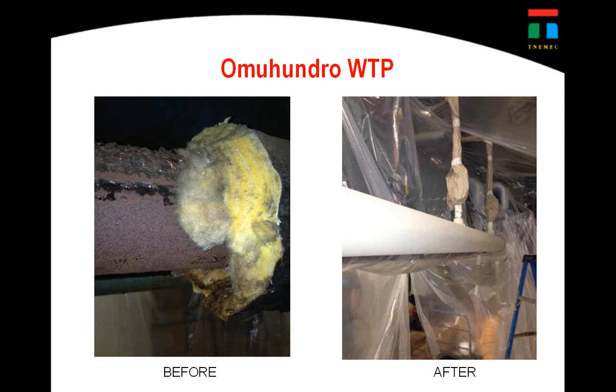So the reason the insulation was placed on the left was to slow down the condensation, not necessarily for R value. So on the right, because you've stopped the condensation, you don't need the R value. Am I correct, or would you still put more on? Well, here's a very interesting approach. There are places where people want to just put down 30 or 40 mils of Aerolon directly on the pipe, and then if they need more insulation, they're adding rigid insulation or other forms of insulation. But now you've stopped the CUI issue.